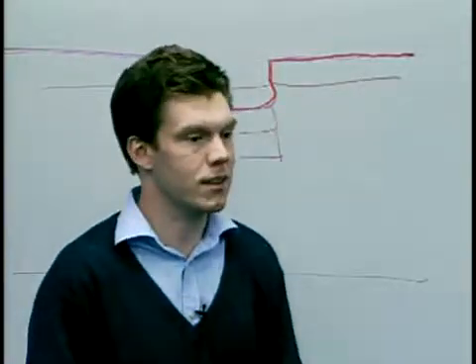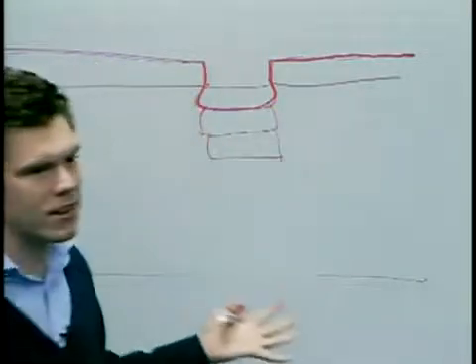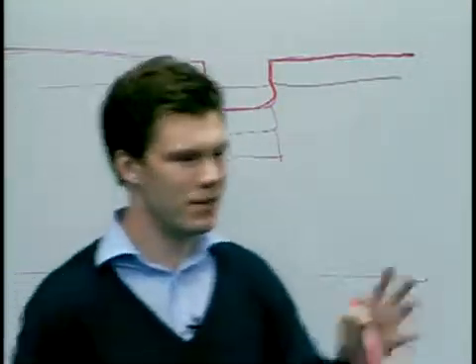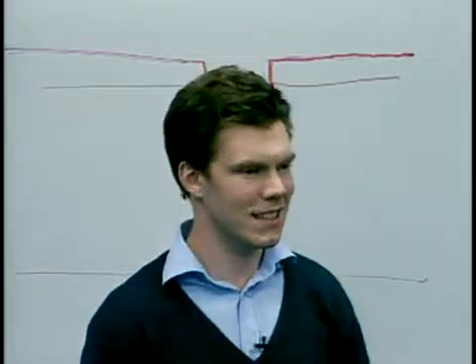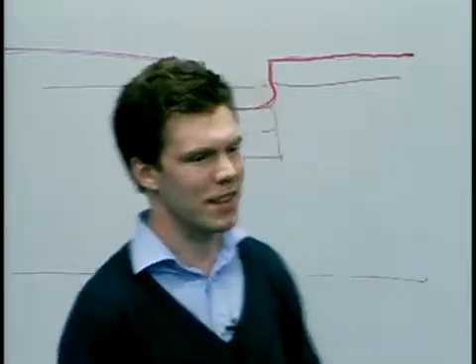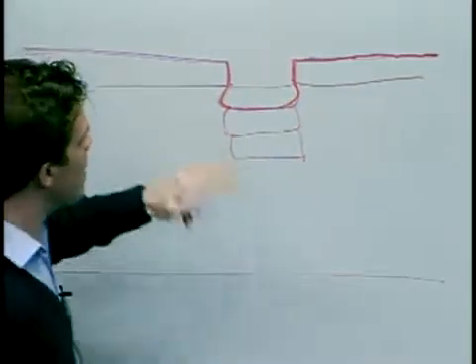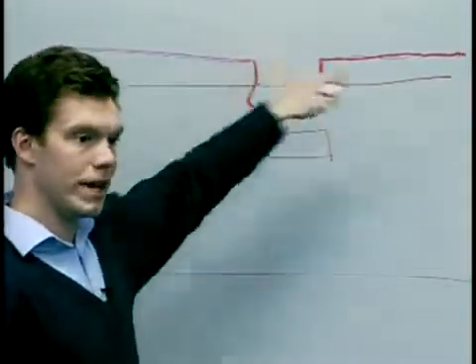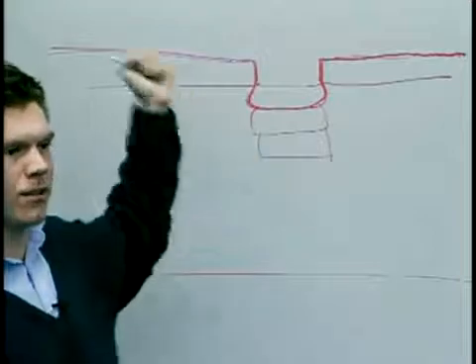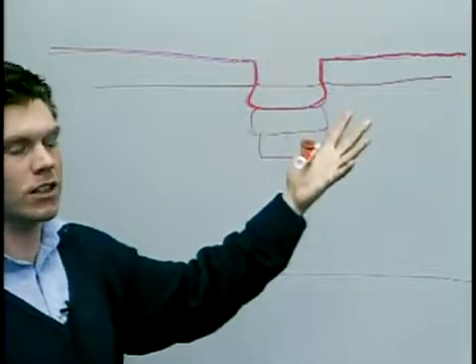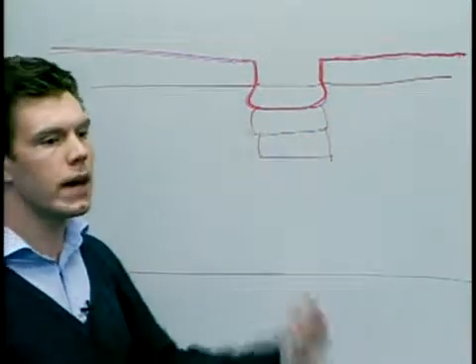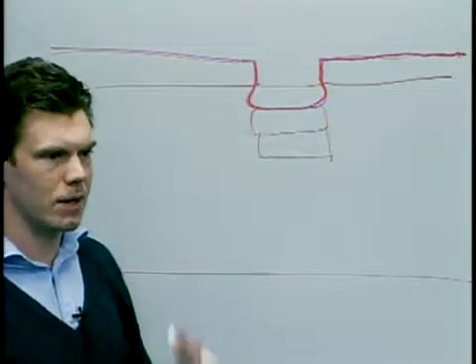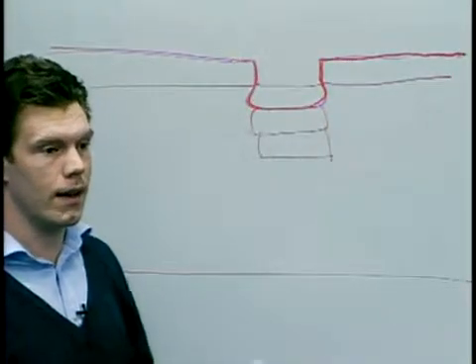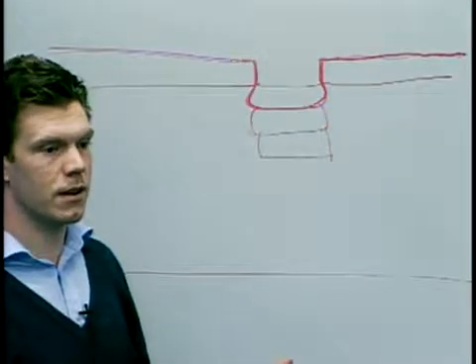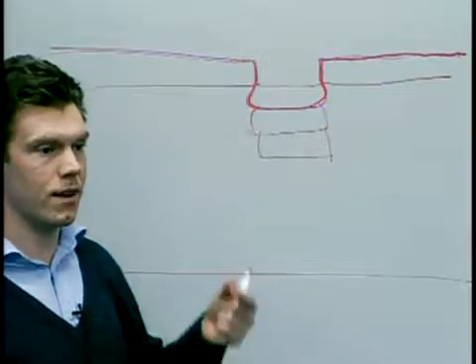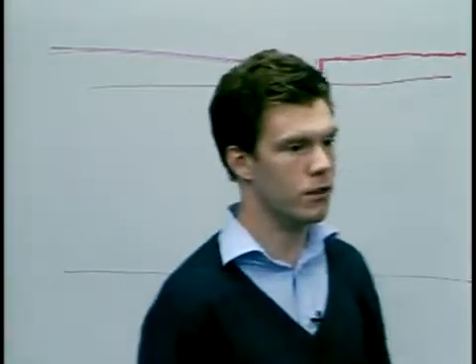Whatever way you pattern the stamp, silicon actually, as we'll see later, for demolding reasons, is a lousy material to use for stamps. So then you might go one step further, electroplate nickel into that etched wafer, peel off the nickel and use that as the stamp, much tougher. Or you might use more novel materials, things like metallic glasses, which are alloys with an amorphous structure that are both very hard and very tough. They would be great materials for a stamp.